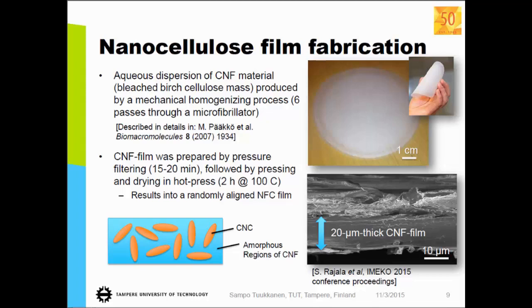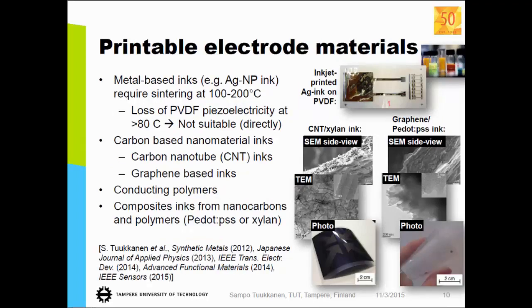There's an SEM cross-section image of about 20 microns thick nanofibrillated cellulose film. And what you have in practice is a kind of these crystalline areas embedded in the amorphous matrix. So this is not the optimal structure, but this is what we have now. And okay, those were the piezoelectric materials, and of course you need also to have conducting electrodes.